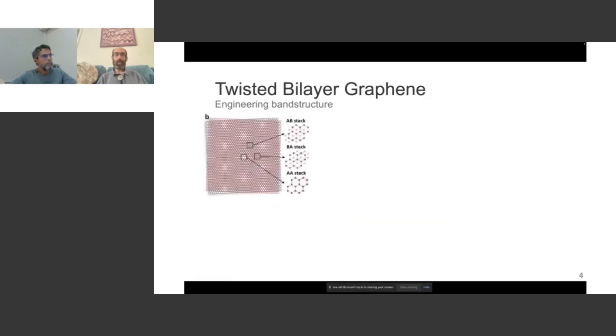And so now, about a decade ago, a number of theorists suggested, and most pointedly, though not first, Rafi Bistritzer and Allan MacDonald suggested that there could be really interesting properties if you look at graphene that's stacked on another piece of graphene with a twist between the two. And so not just stacked in the sort of simple periodic relations that I showed you, but with a small twist between the layers. And what you can see here is if you have a twist between the two layers, the two layers go in and out of registry with each other, and you get a pattern that shows up on a scale much larger than the atomic lattice scale as the two go in and out of registry.